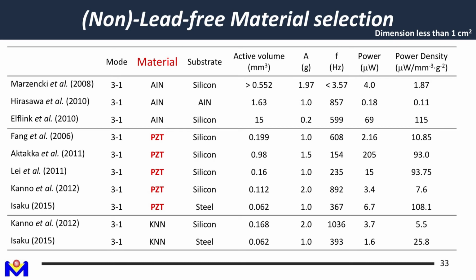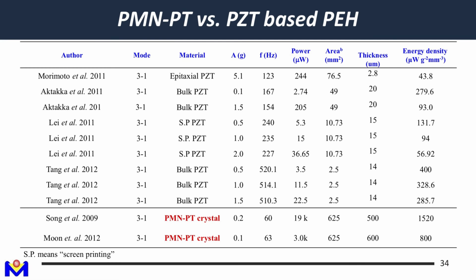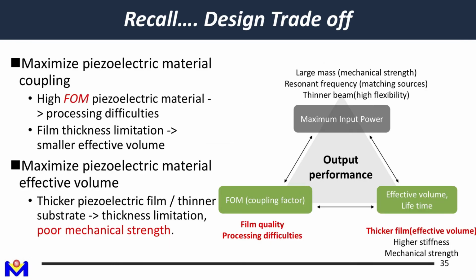Okay, so let's continue with some literature. If you are interested, you can trace it by yourself later. So again, let's recall the design trade-off. Now we are talking about the material figure of merit and also the piezoelectric effective volume, including lifetime. So here, if you want to maximize the piezoelectric material coupling, we want a higher figure of merit piezoelectric material. But in general, for example, we can try to grow epitaxial single crystal material, but the processing difficulty is much higher. For example, quartz is a hard single crystal material.